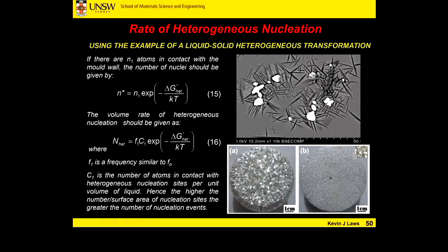And again, if we give a greater number of nucleation sites, and here's our example from Monday's class, if we add our inoculation particles, without inoculation, we get this crystal structure, this number of large grains. With our inoculating particles, we're giving multiple sites for nucleation to occur.